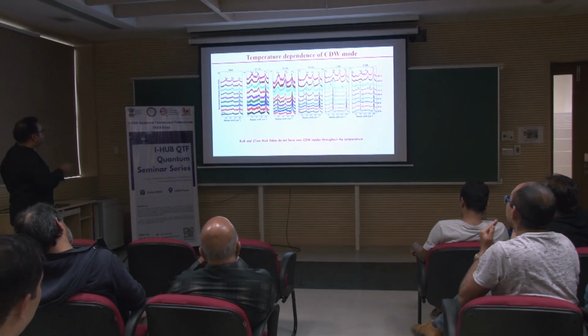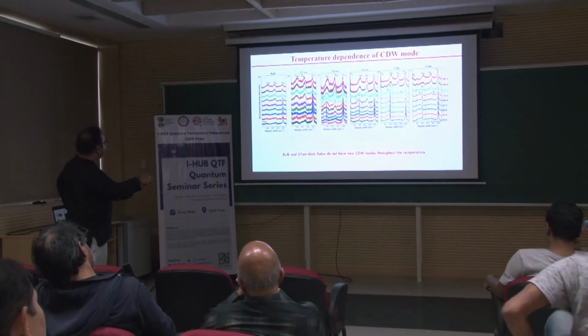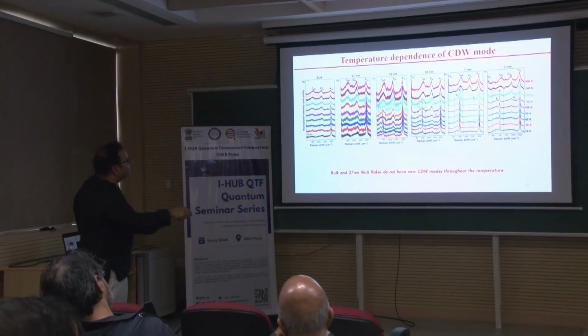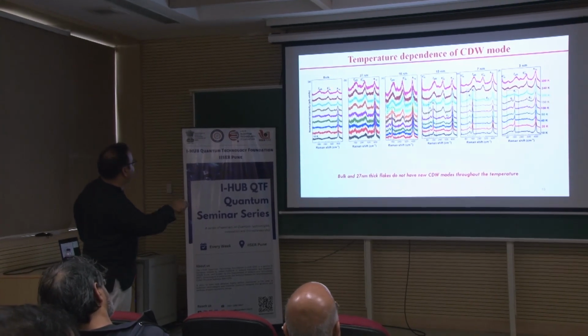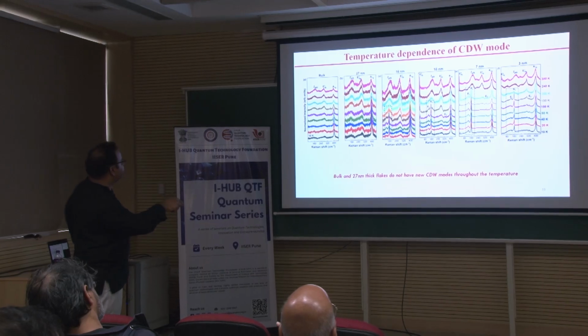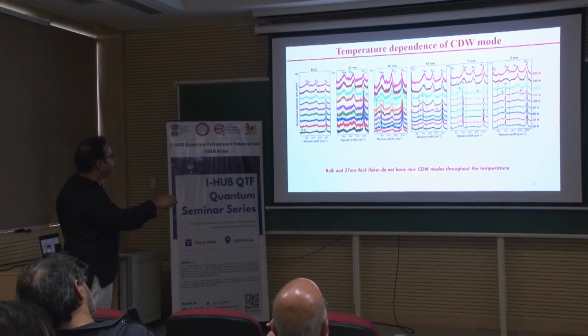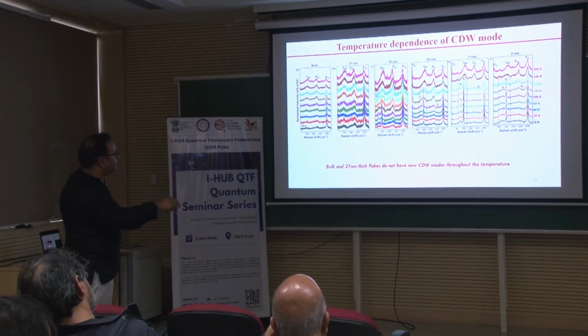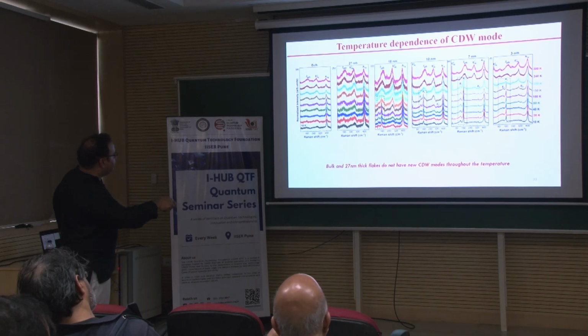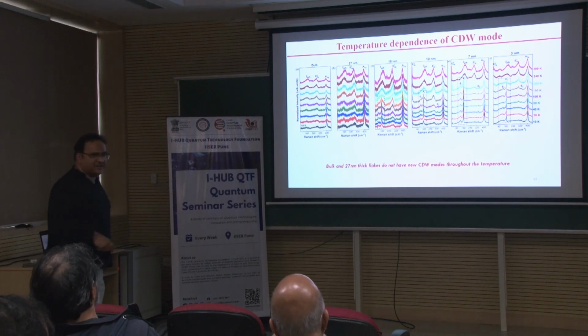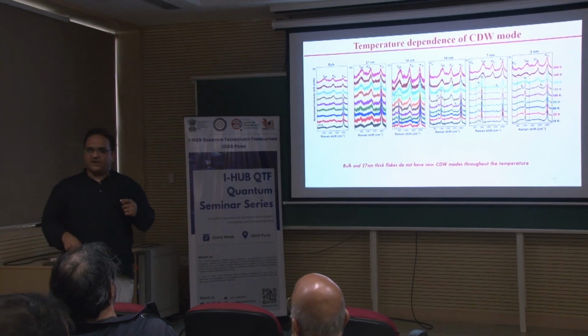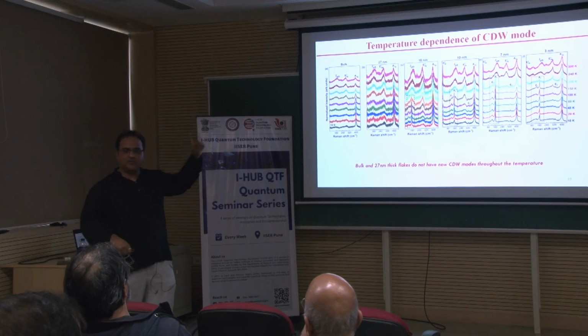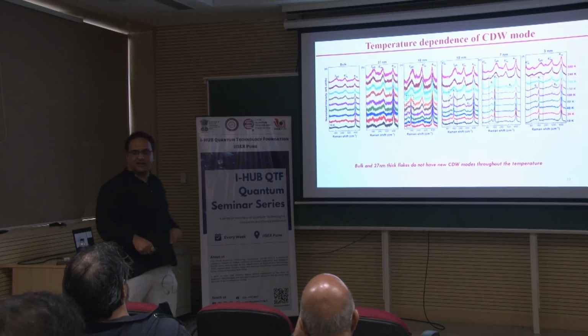So, this is bulk and this is 10 Kelvin here. This is the temperature scale: 300 Kelvin, this is 10 Kelvin, 27 nanometer, 16 nanometer, 10 nanometer, 7 nanometer and 3 nanometer. So, I have new modes which are coming up below 16 nanometer, not existing at higher thicknesses. So now you have charge density wave modes and modes which are coming up because of the dimensionality effect here.